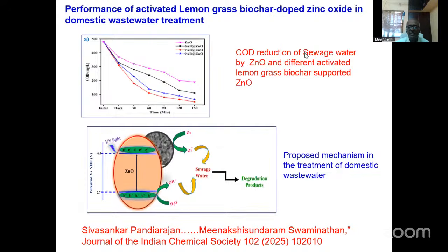This is another biochar that we prepared recently using lemongrass. So this is a lemongrass biochar, and then we treated sewage water, and we found that the 7% activated biochar zinc oxide was most efficient. And here also the mechanism is the same, simple: the biochar abstracts the electron from the conduction band of the zinc oxide and gives it to oxygen, and this is separated, producing OH radicals.